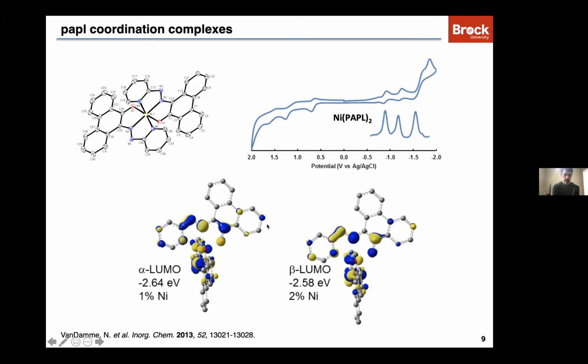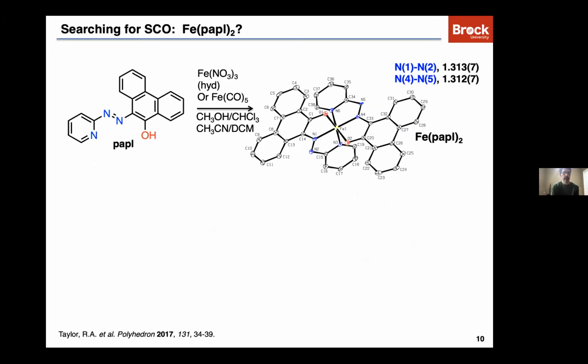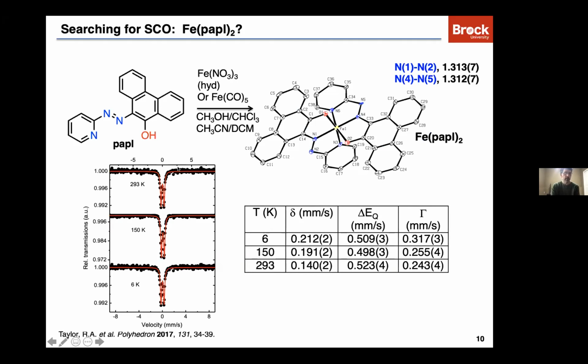Now if you make an iron complex, what do you get? Do you get spin crossover? Well, you can take PAPL, coordinate it to almost any source of iron you want, iron 3, iron 2, or iron 0, and you always get the same thing. You get an iron 2 complex, neutral, with 2 coordinated PAPL anions. And in this case, you see from the Mossbauer spectra over different temperatures that this is completely low spin, diamagnetic. There is no spin crossover in the system.